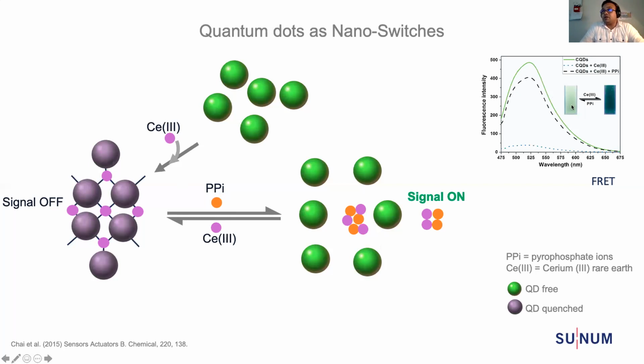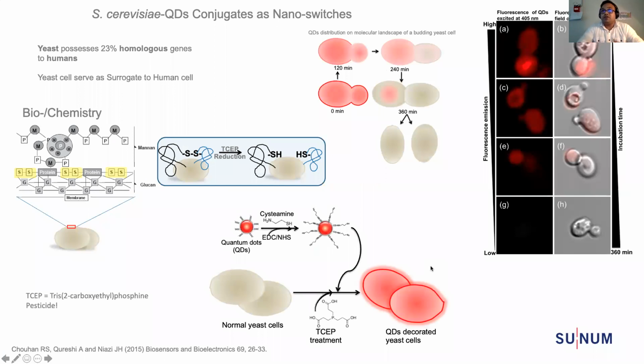As you can see here, in normal conditions, quantum dots are clear. They start to emit light as you excite them. But in the presence of cerium, the signal is off. You essentially see no light coming out of the crystals. But when you put pyrophosphate back into the solution, it bounces back with emission of light. This phenomenon was exploited in our study. This is a long time ago. The work actually started somewhere in 2013, and was published in 2015.